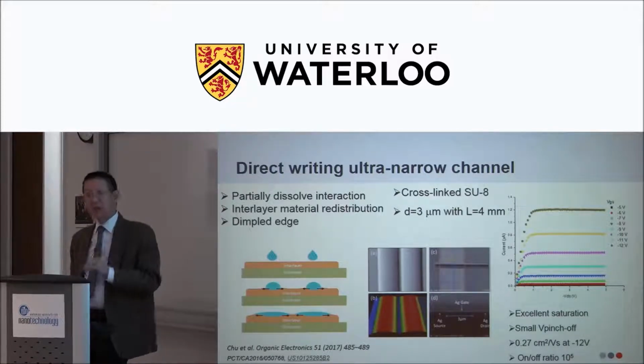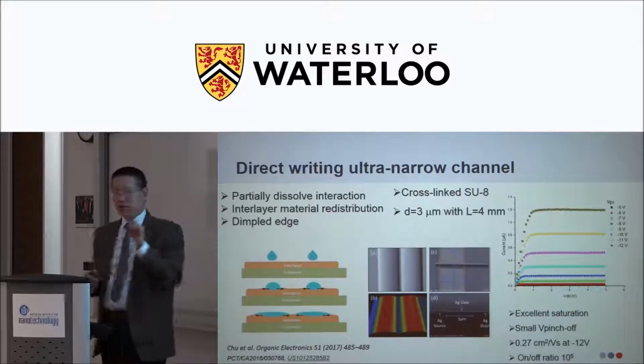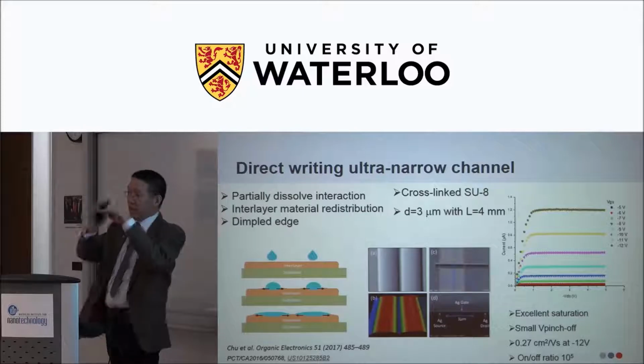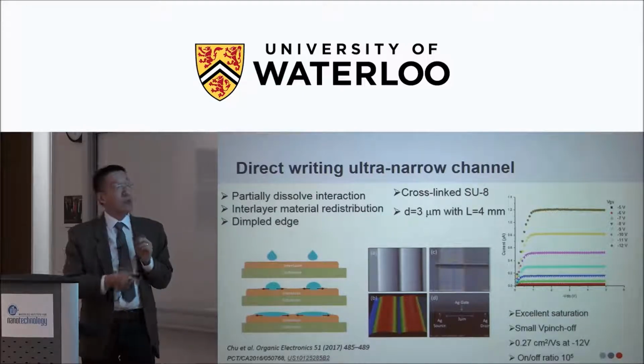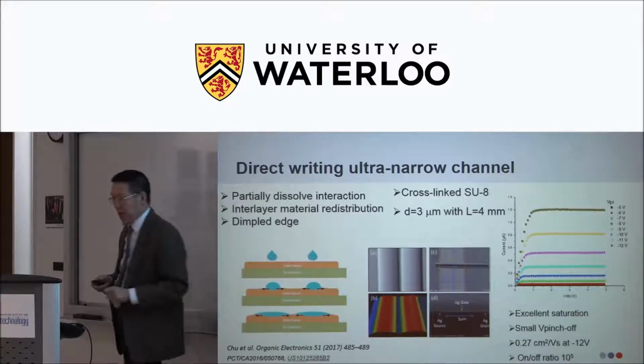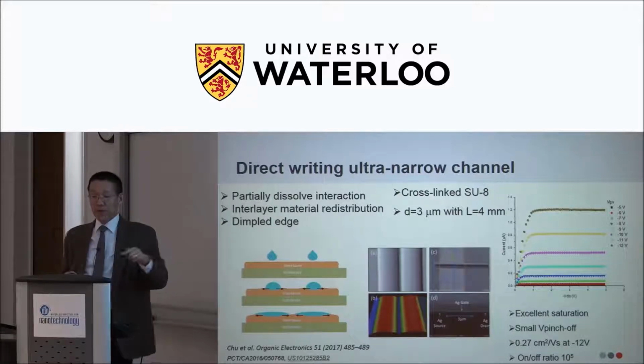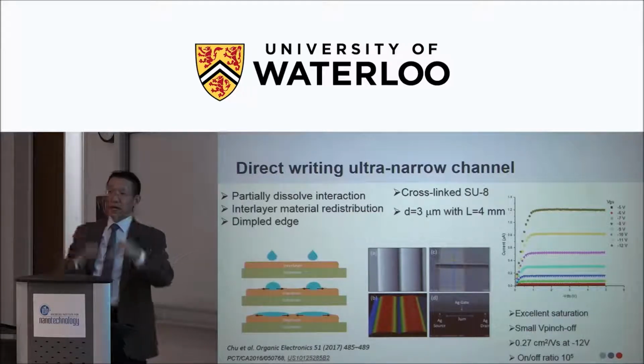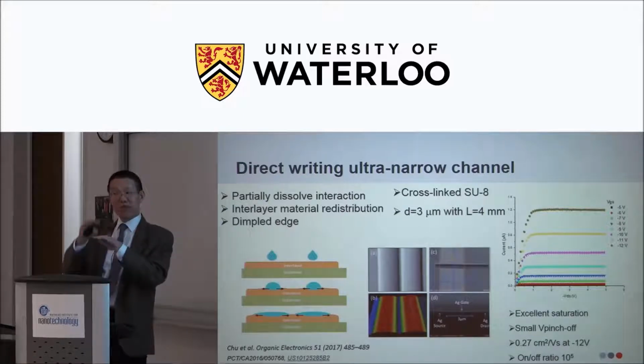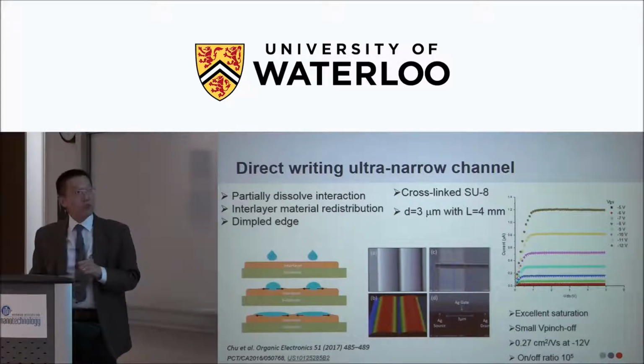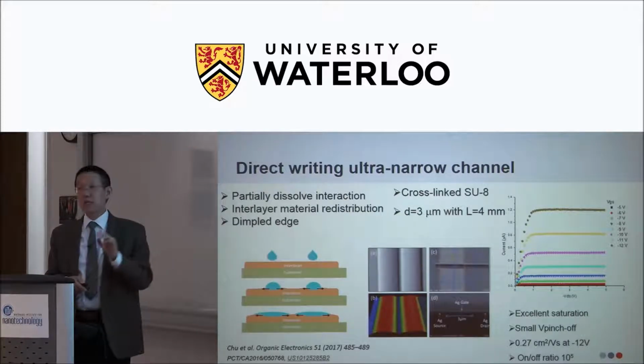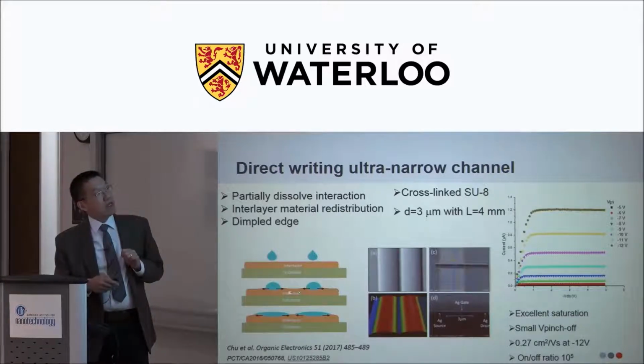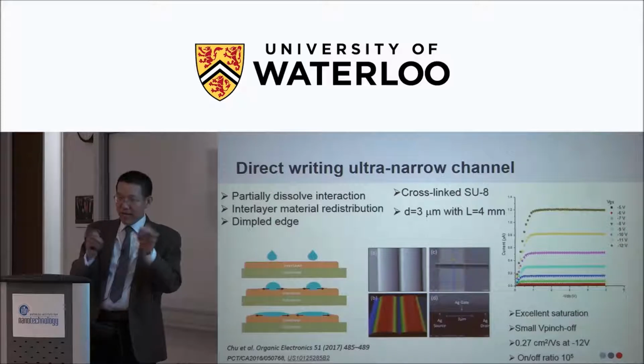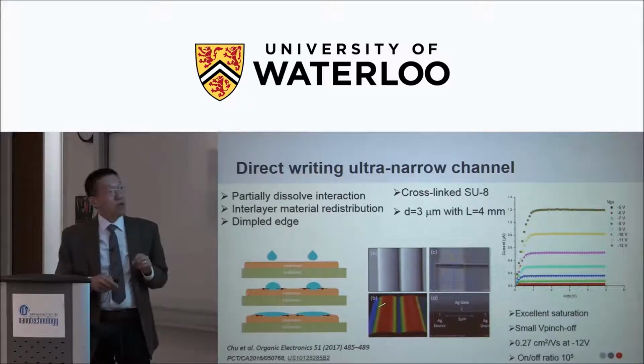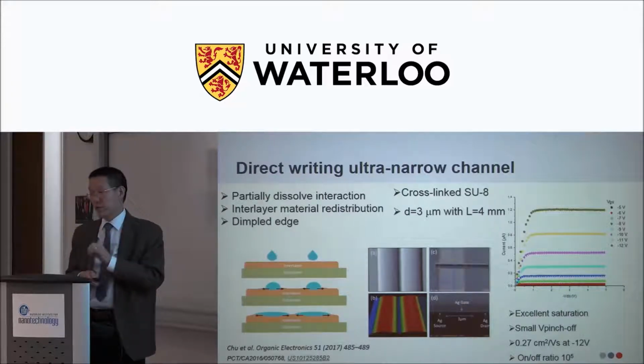What we did here is use a cross-linked SU8, and the solvent in our ink can dissolve a tiny amount of SU8 and form an ink bank. They push that towards the side of the inkjet and form an ink bank. We can reproduce this channel very reliably, down to 2 to 3 micron channel length. Anything below that, you have to do another formula. You can make that, but the surface becomes rough, so they are not very suitable for transistor application. But for 2 to 3 micron channel length, it's very reproducible. So by doing that process, we add an interlayer and use this slightly dissolved SU8 as bank material. You can well define the channel length down to 2 to 3 micrometers.